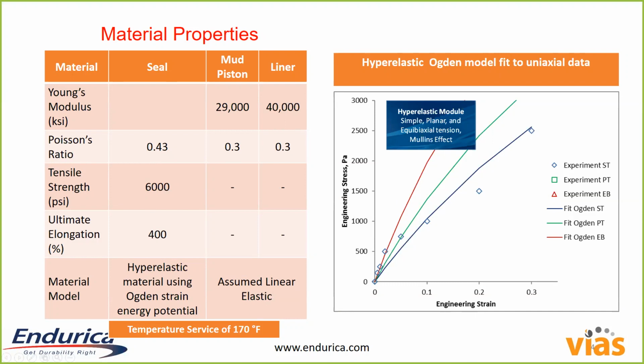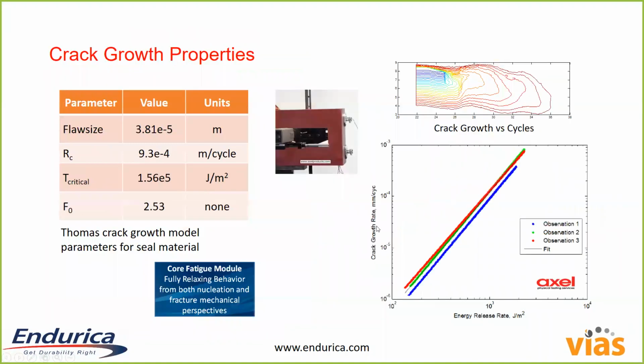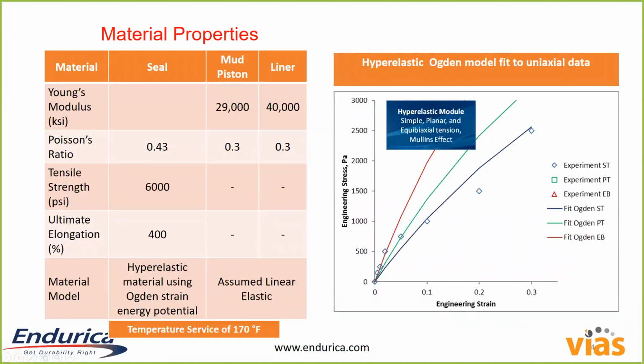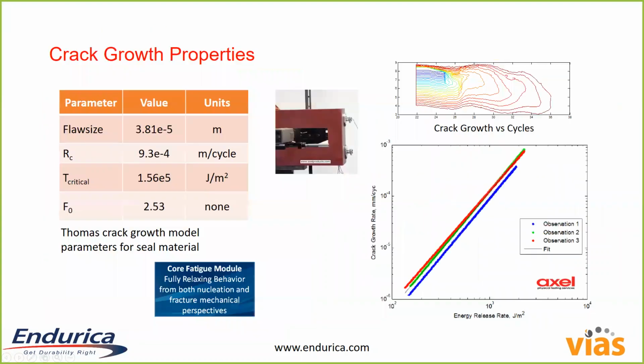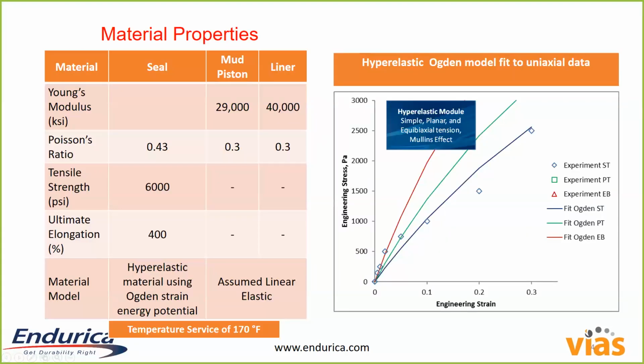hyperelastic law. The blue curve shows the simple tension response of the material law. For those who are familiar with using a hyperelastic law, it is typical to do experiments in planar tension and biaxial tension. So the green and the red curves are the planar and the biaxial stress strain curves that are predicted from our model. Here we haven't measured those, but we would certainly normally recommend measuring all 3 stress strain curves with our hyperelastic module. I should also mention that the service temperature we're going to analyze is 170 degrees Fahrenheit.